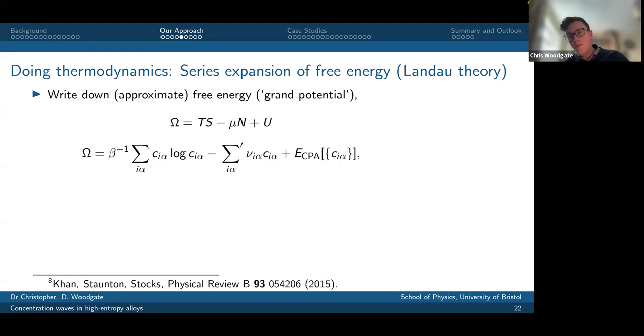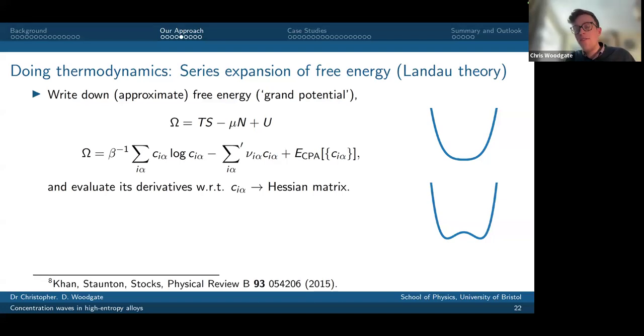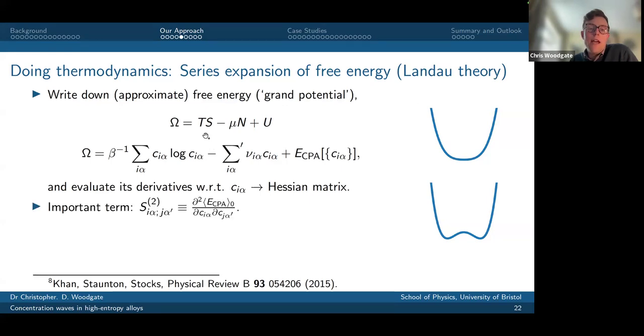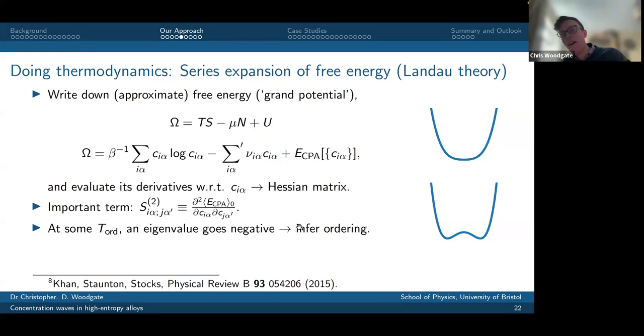Due to symmetry, the first derivatives of this free energy around the homogeneous reference state can be shown to vanish. What I have to look at then is the second concentration derivative, and that means I build up an expression for a Hessian matrix. You can do the concentration derivatives of the first 2 terms by hand pretty trivially, but the challenging thing to evaluate is the change in energy of the CPA reference medium, and that's what the S2 theory gives me access to. What I look at then, in some sense, is the eigenvalues of my Hessian matrix. At high temperature, my Hessian matrix is strictly positive definite. All eigenvalues are positive, and the system is stable to chemical fluctuations. But at some finite temperature, I anticipate that at least one eigenvalue passes through 0, which tells me that I've gone from a high-dimensional bowl of free energy to a situation where I have little local minima emerging, and the system can move into an ordered or partially ordered phase.